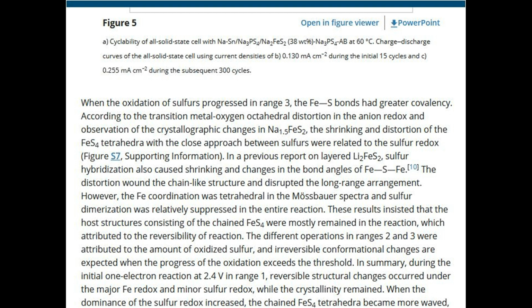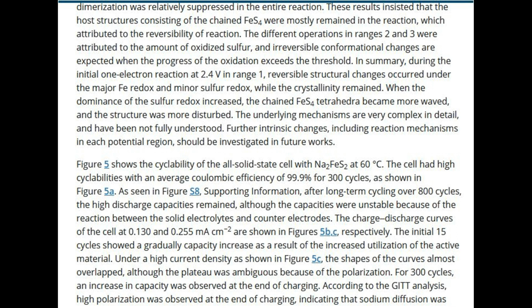In summary, during the initial 1-electron reaction at 2.4 V in range 1, reversible structural changes occurred under the major Fe redox and minor sulfur redox, while the crystallinity remained. When the dominance of the sulfur redox increased, the chained FeS4 tetrahedra became more waved, and the structure was more disturbed. The underlying mechanisms are very complex in detail, and have not been fully understood. Further intrinsic changes, including reaction mechanisms in each potential region, should be investigated in future works.